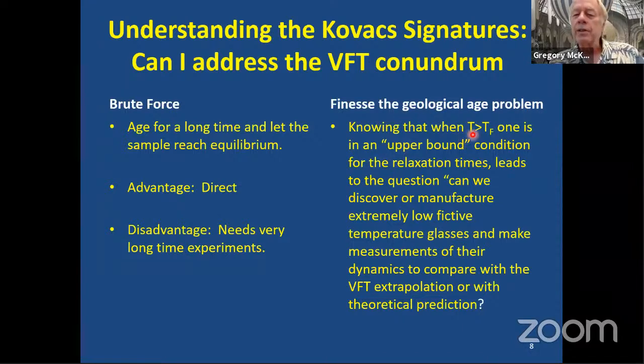Or the other question, and this is understanding this problem of finessing this geological age problem. So if I know that when T is greater than the fictive temperature, we're in an upper bound condition for the relaxation times. And so that leads to the question, can we discover or can we manufacture extremely low fictive temperature glasses and make measurements of their dynamics to compare them with the Vogel-Fulcher extrapolation or with the theoretical prediction of behavior below the glass transition?